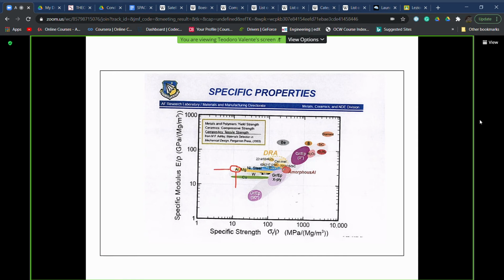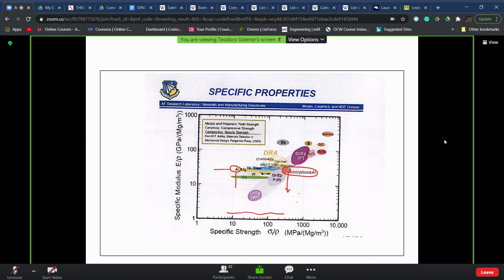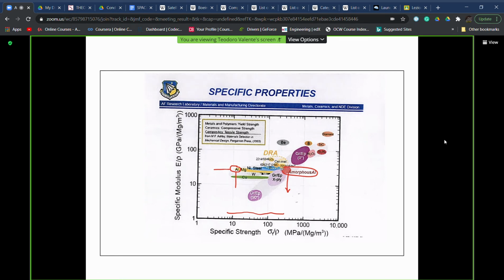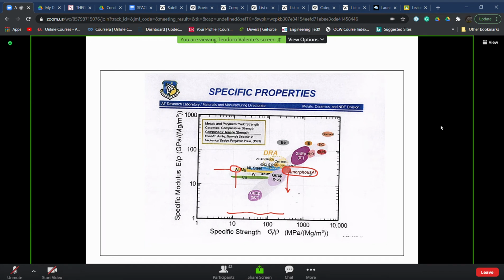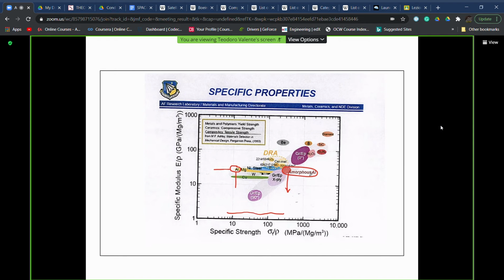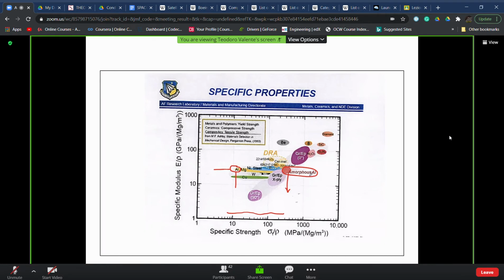If we go to the area of the amorphous aluminum alloys, that is bulk metallic glasses based on aluminum composition, this is a log scale, you see here, we have a very relevant increase in specific strength due to the fact that we have said before. Even though it depends on the formulation, the specific modulus is more or less comparable. But the increase in specific strength has been proved, is expected, and is obviously a benefit for the possibility to fabricate these special and, let me underline, very expensive components. So they cannot be found in conventional applications using the concept of metallic glasses.